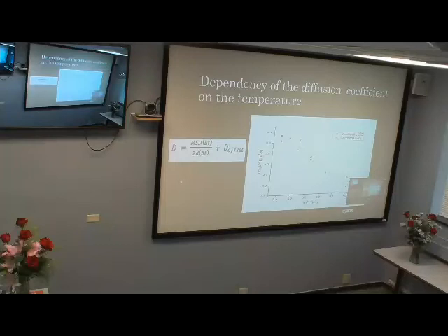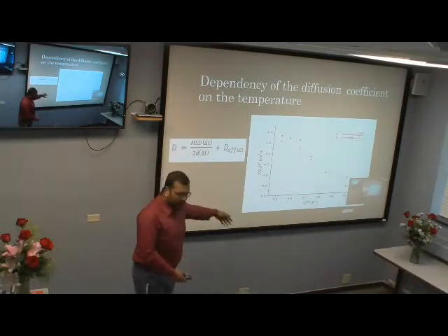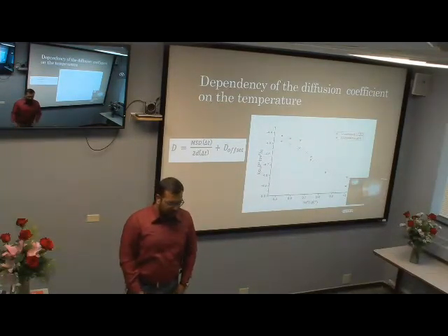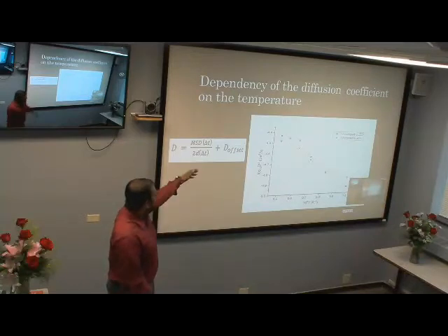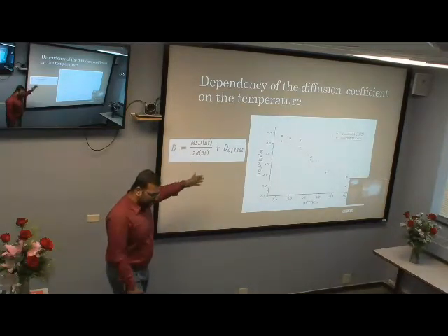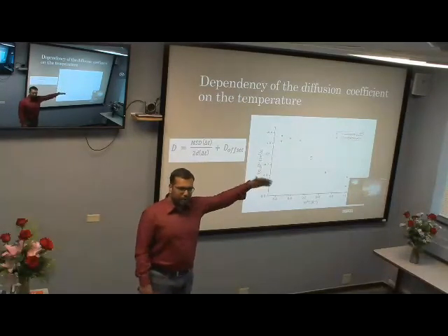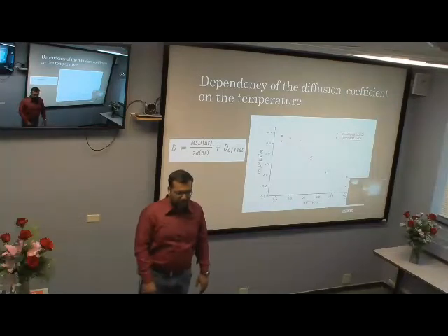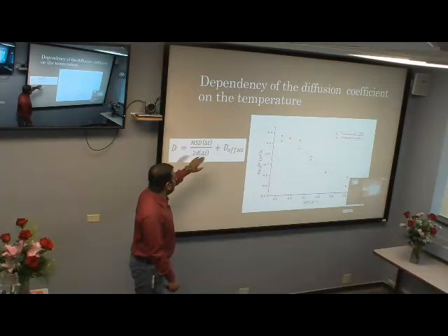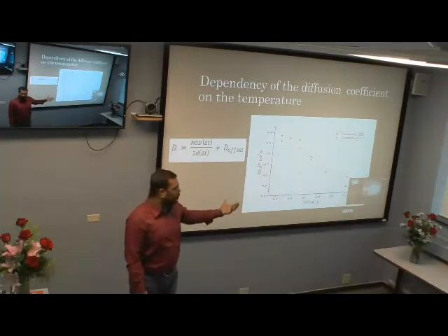So that is the third part of the whole calculation or whole plan. In this part I have calculated the diffusion coefficient and the activation energy. How have I done that? I have basically followed this simple equation. After the molecular dynamics, I plotted the mean square displacement versus time step graph, which gives me the slope, mean square displacement divided by delta T. And with this equation, I have calculated the diffusivity at each of the temperatures.